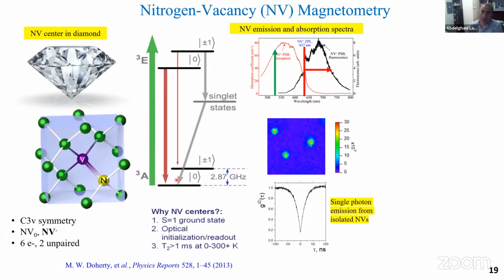How it works: usually we shine a green laser. The NV emits light in the range of 650 to 750 nanometers. By using confocal microscopy detection, for example, we scan the sample. You can see these isolated bright spots, and these are single NV centers. The most interesting thing about this defect is that it emits single photon light. If you do the G2 measurement, you see a very well-defined G2 below 0.5, indicative of single photon emission. So NV also applies very well to photonics and quantum photonics applications.